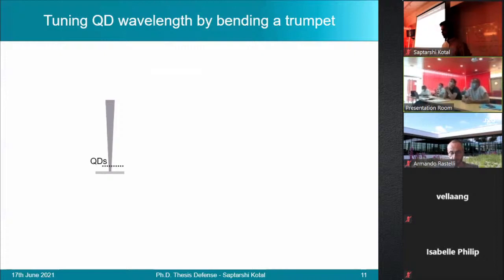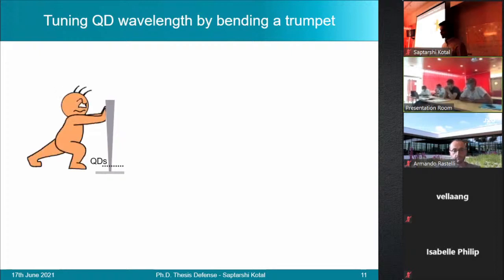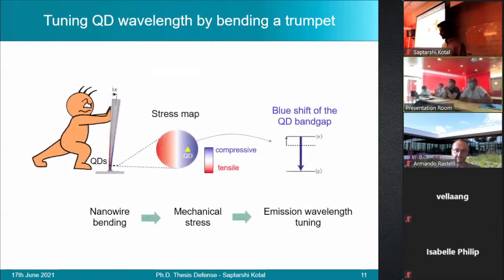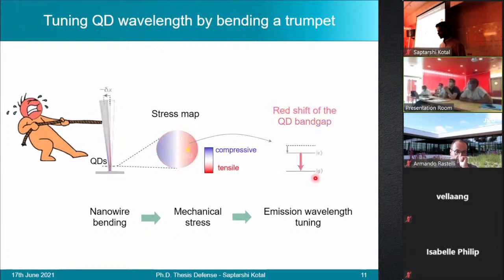Now, the principle that was used to tune the quantum dot in the trumpet was to bend the trumpet. Now, as the trumpet bends, a part of the trumpet is compressed, while the other part is stretched. So this results in a stress gradient across the quantum dot plane. Now, when the quantum dot experiences this stress, which is predominantly uniaxial and directed along its growth axis, if it's compressed, it undergoes a blue shift in its band gap. And if it's stretched, then it undergoes a red shift in its band gap.